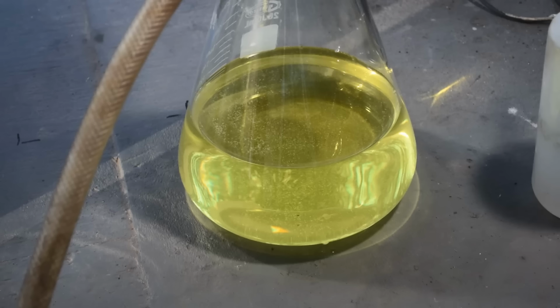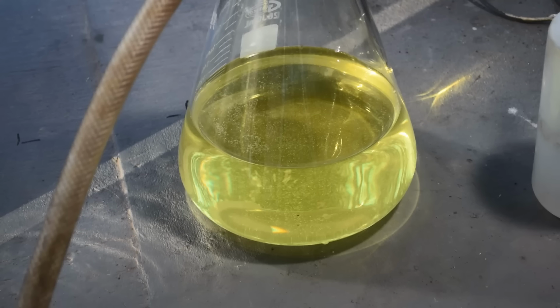I suppose it's too late. Tomorrow, before I refilter it, I could put a squirt of sulfuric acid in there and make sure we get any and all lead out that way. But yeah, I'm going to put this in the fume hood and leave it until tomorrow and then deal with it. Then I will refilter it and then we will drop the gold. And hopefully we'll get a nice clean filtrate then and nice clean gold. So see you in the morning.